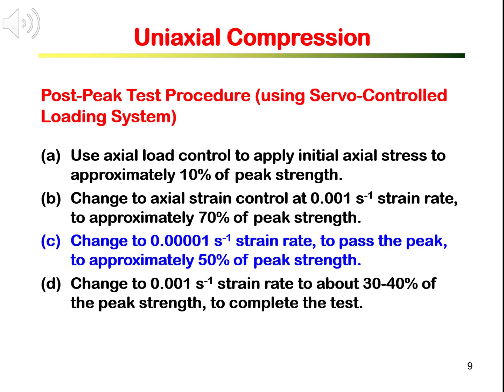Again, the specimen and the specimen assembly with strain measurements are positioned in the servo-controlled loading machine. We start by using axial load as the feedback control to apply an initial axial stress of approximately 10% of the peak strength. The specimen is now in the elastic behavior region. We now change the feedback control to axial strain control and set the axial strain rate at 0.001 per second.